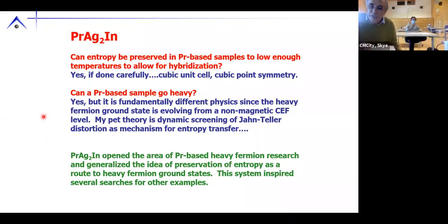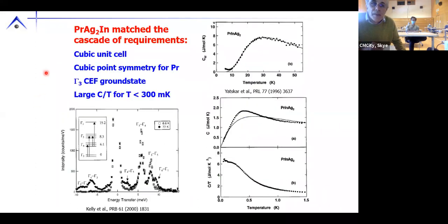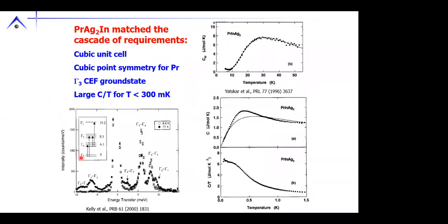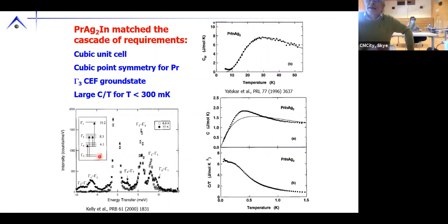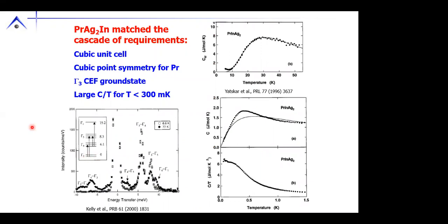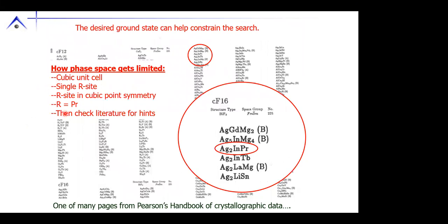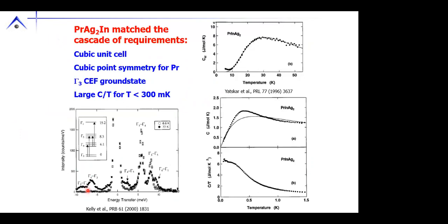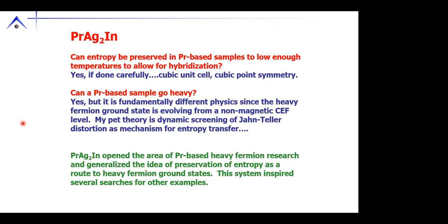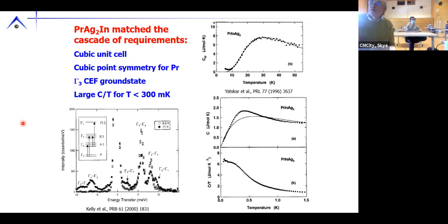All right. Question, just to interrupt things. Can you remind us, do any of these praseodymium systems have doublet ground states? Or are they all singlets? The whole point of this discussion was we very carefully preserved the Gamma 3 doublet. So no, the whole point was I wanted to have this cascade to then see if I could get a gamma 3. And indeed, praseodymium silver 2 indium has that, and as does praseodymium lead 3. But in this case, we seem to avoid a cooperative Jahn-Teller, and it goes heavy. So it's entangled with its surroundings somehow.